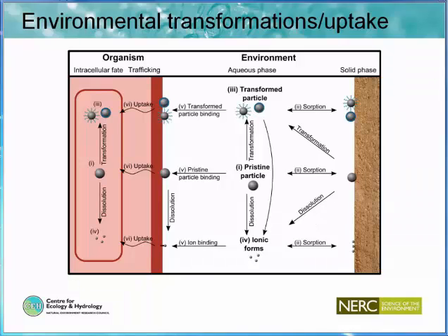The other aspect which guides us in our research is what we know, or what we think we know, about the environmental transformations and uptake of nanoparticles once they actually get out into the environment. This is highly dependent on the type of nanoparticle, but for the ones that we're mostly interested in, metals and metal oxides, processes such as dissolution and loss or replacement of a capping agent, if there is one, could be important in determining the behavior of the nanoparticle and therefore its bioavailability and its toxicity in the environment. And we can construct conceptual models such as this to guide us in the environmental factors which we might want to consider in our research.